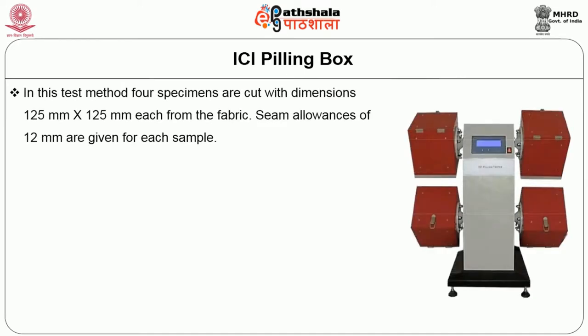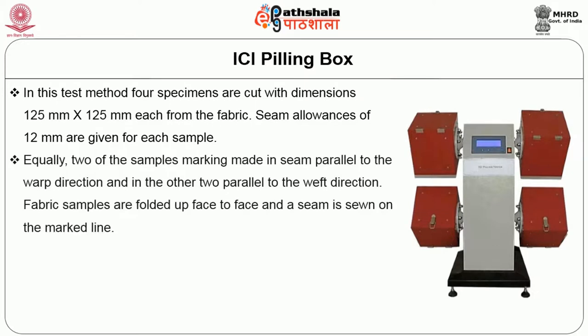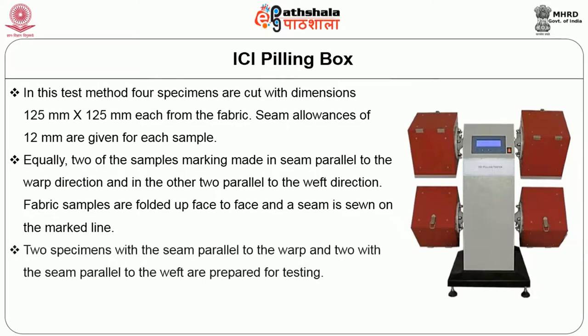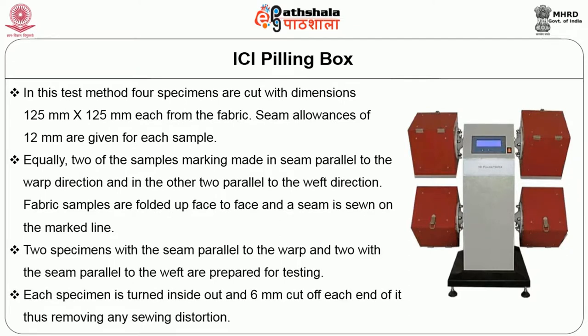In this method, 4 specimens are cut with dimensions 125 mm by 125 mm. Seam allowances of 12 mm are given for each sample. Equally, 2 of the samples are marked with the seam parallel to the weft direction and 2 with the seam parallel to the warp direction. Fabric samples are folded face to face and a seam is sewn on the marked line. 2 specimens with the seam parallel to the warp and 2 with the seam parallel to the weft are prepared for testing.